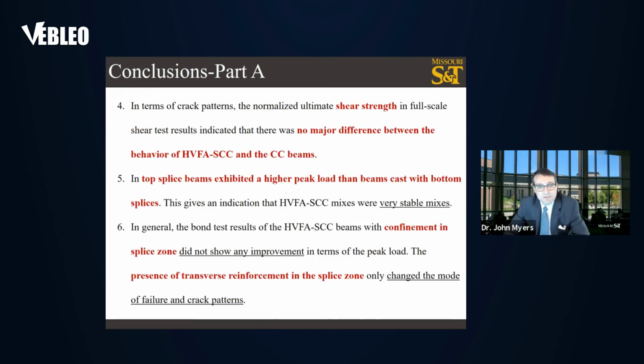In terms of shear strength, there was no major difference between the behavior of this new mix and conventional concrete beams. The top splice beams exhibited a higher peak load than beams cast with bottom splices, and usually it's the opposite. So this showed us our mix was very well distributed.